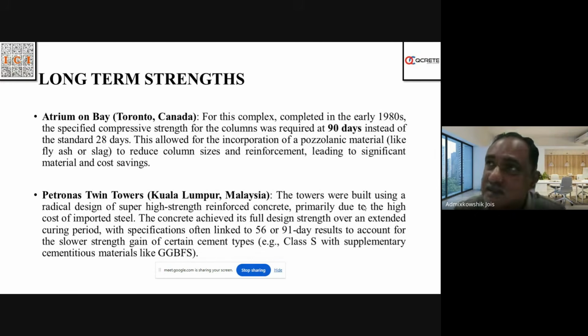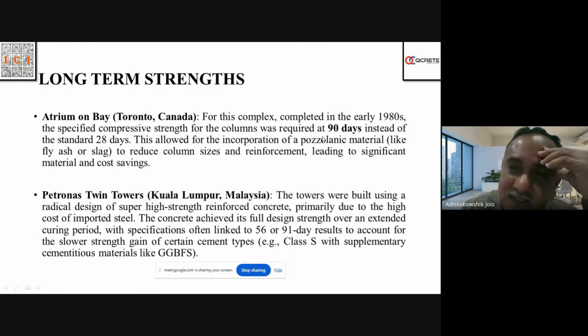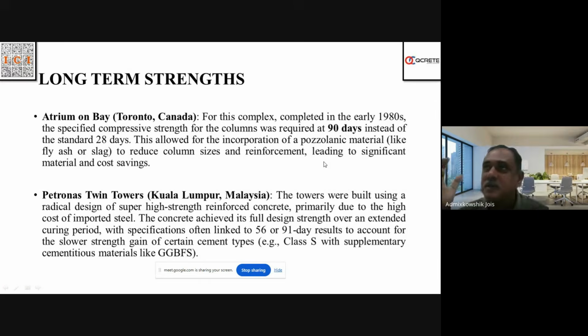So even if the 28-day strength is not good, not up to the mark, there are considerations based on site requirements, based on your experimental data. If you have proper data, it can be used. For example, in tall buildings and skyscrapers in Toronto in the 1980s itself, the compressive strength was specified at 90 days instead of the standard 28 days. That allowed the incorporation of pozzolanic material. This allowed a lower amount of OPC and a higher amount of pozzolanic materials, lower 28-day strength but higher 90-day strength. The specification was that the concrete has to meet the requirements in 90 days.